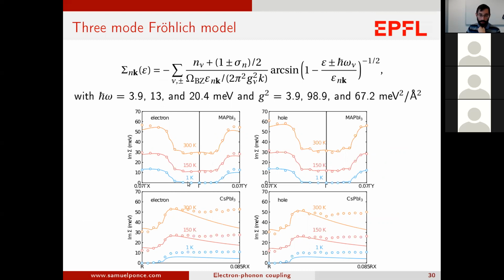As a function of k space, but we assume here band parabolicity, and therefore there is a direct connection between k and the energy. And so what is quite remarkable is that with only 3 phonon frequencies, which are the 3 dominant ones that I've shown, so those 3 phonon frequencies, 3.9, 13, 20, and the associated electron-phonon matrix elements, which is just 3 numbers, we can reproduce the ab-initio data very accurately, but also in temperature. So note that there is no temperature parameter. It's all contained within those Bose-Einstein distribution functions. And so both for the electron and the hole, with only those, let's say, 3 or 6 parameters, we can reproduce those bumps. So the first bump is due to the first mode, second mode, third mode.